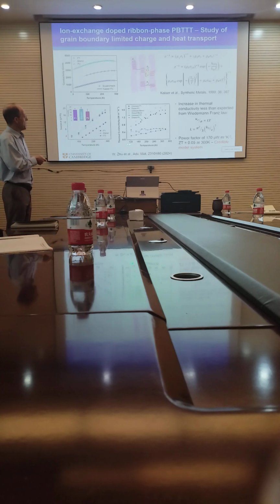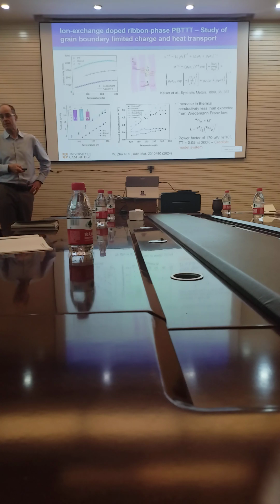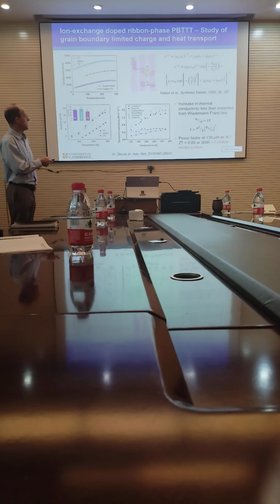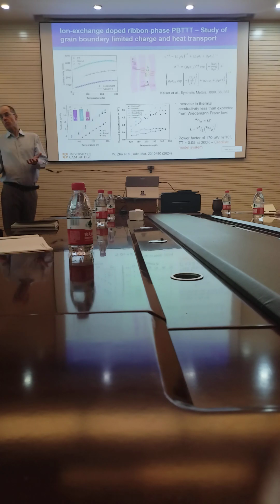What's interesting here is the thermal conductivity. I want to just highlight that a little bit. So this is the thermal conductivity as a function of temperature. These data points here are the undoped system. So that's just the lattice thermal conductivity. There's not much difference between the blends and the neat polymers at room temperature in terms of their lattice thermal conductivity. When you dope, of course, the thermal conductivity increases because the electrons carry heat, so the electronic contribution to the thermal conductivity is important.